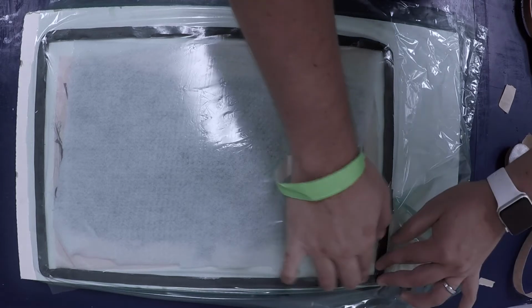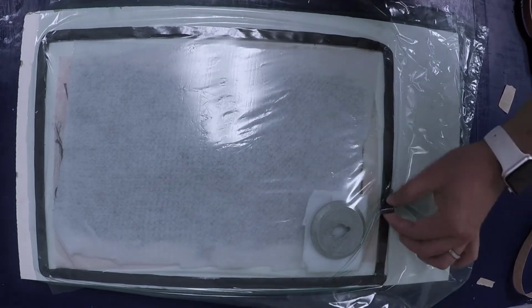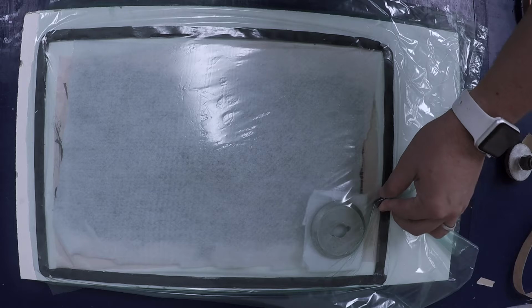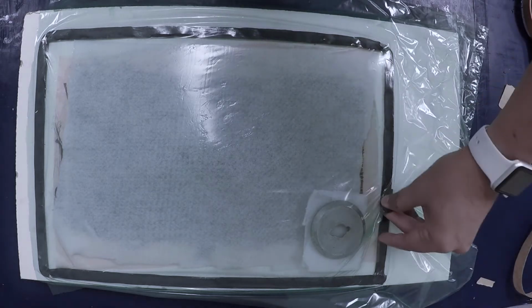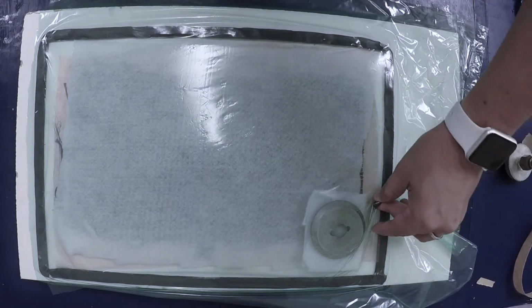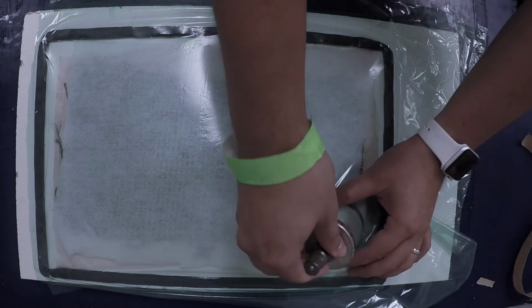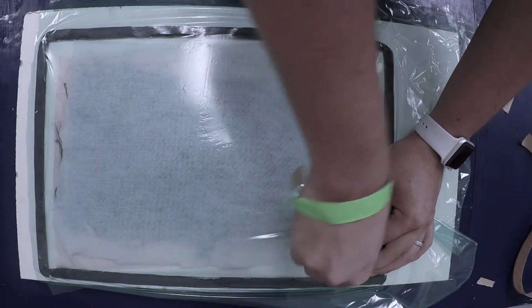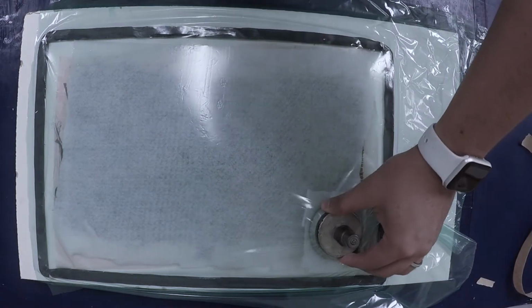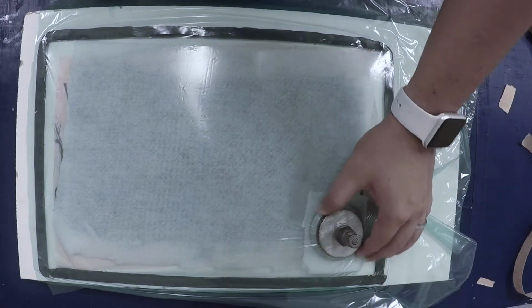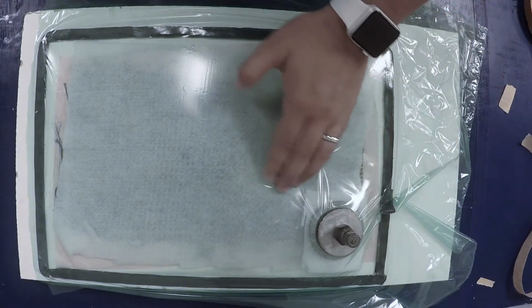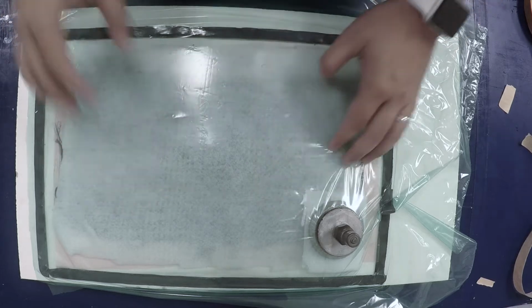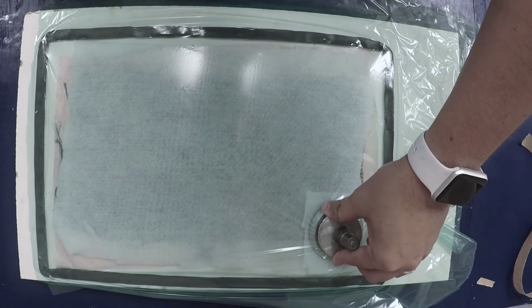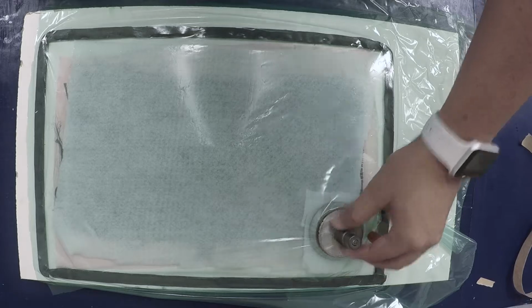Once you are satisfied with the appearance of the seal between the tacky tape and the bag, you may cut a small hole over the vacuum port with some scissors. This will allow for the top portion of the vacuum port to connect with the lower portion. When joining the two halves of the vacuum port, be sure that no wrinkles from the bag are trapped in between. These wrinkles will create vacuum leaks that become very hard to find. To ensure a perfect seal, firmly twist the top half to seal with the bottom.